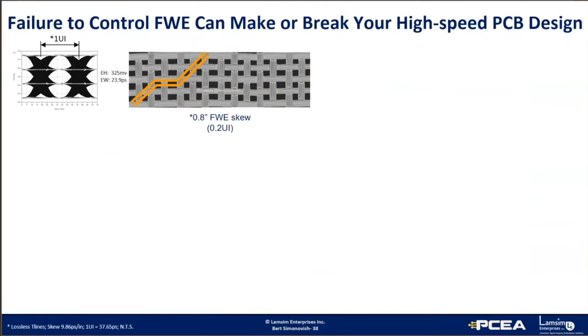Here's an example of fiber weave effect on a lossless differential pair. In reality, though, there's no such thing as a lossless transmission line, but it's used here to isolate any losses due to the skew. On the left is a 26.56 gigabaud PAM4 with 0 picoseconds of skew. With 0.2 UI of fiber weave effect and 9.86 picoseconds per inch of skew, that represents about 0.8 inches.